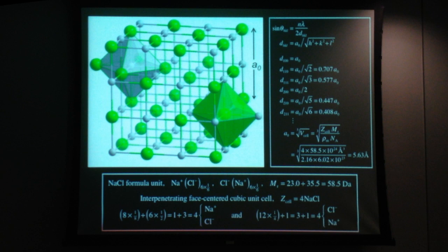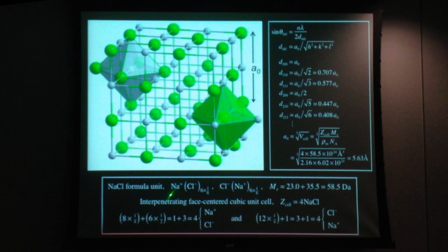So for the sodium chloride formula, we have around each sodium ion six chloride ions, but they're shared with six other sodiums. Right? So six times one-sixth, one chloride per sodium, and similarly here. Okay? So we can say that there's this one-to-one formula. The molar mass would be the atomic weight of sodium plus the atomic weight of chloride. Okay, we know the molar mass. Avogadro had worked things out pretty well before the fact, Avogadro and company. So they knew the molecular formula and molar mass for sodium chloride.